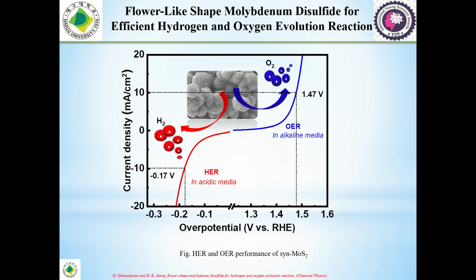And this is the electrocatalytic performance of our synthesized MoS2. We can clearly see the hydrogen evolution reaction. There was very low overpotential after nickel doping, investigated at a current density of -10 milliamperes per square centimeter. An overpotential of 0.17 volts appeared in acidic media. And in alkaline media, we performed the OER, oxygen evolution reaction. A lower overpotential also appeared.